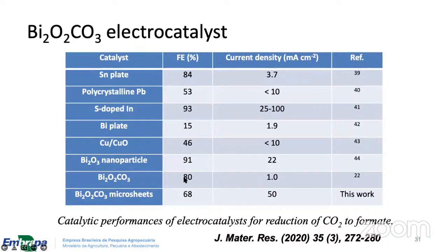But the most interesting aspect that we got using this strategy is to increase the current density of these catalysts. We see in the literature some examples like this one used as a reference for us, the sulfur-doped indium, which can have current densities around 100 milliampere per square centimeter, which is a target for us. But using the bismuth oxycarbonate microsheets, we got a current density of 50 milliampere per square centimeter, which is a good number for the current stage of our research.